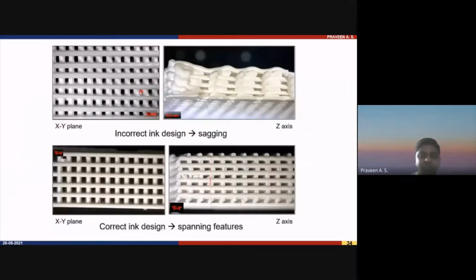Here you see, at the top, as I told you, in direct ink writing we can develop a lattice structure or a spanning structure like this. But because of improper ink design or inappropriate solid content, the structure got collapsed. Each printed line doesn't have the strength to withstand the line printed above it. This is because of improper ink design. But when we tune the viscosity, or add more solid loading, we are able to achieve the desired spanning structure. So ink rheology and ink design are very important factors when we go for direct ink writing of ceramics. We have to keep this in mind.